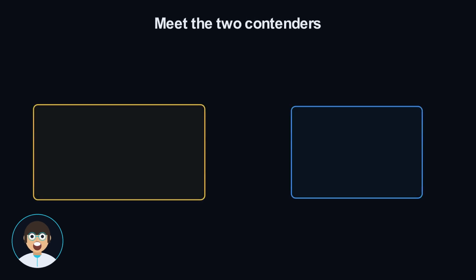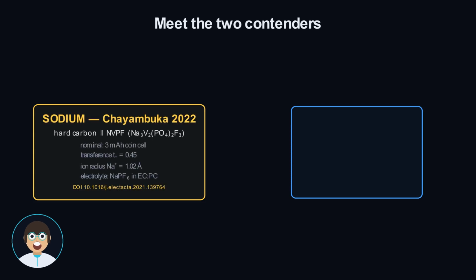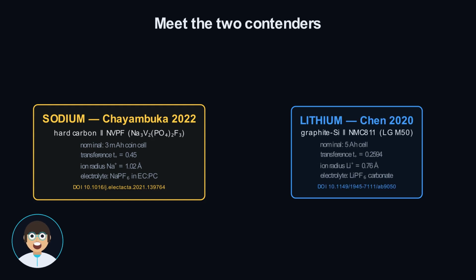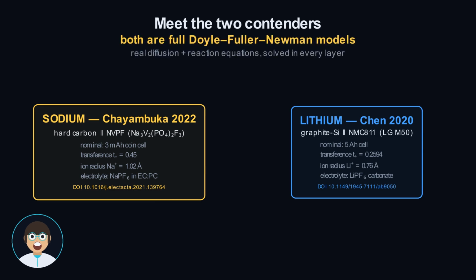Now meet our two contenders, and these are not toys. They are peer-reviewed physics models, the very same ones researchers publish with. Sodium is the Chayambuka 2022 model, a hard carbon electrode against an NVPF electrode, published in Electrochimica Acta. Lithium is the Chen 2020 model, graphite and silicon against nickel-rich NMC, the famous LG cell, from the Journal of the Electrochemical Society. Both are full Doyle-Fuller-Newman models. They solve the real diffusion and reaction equations through every single layer of the electrode.